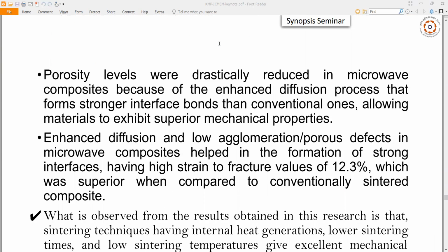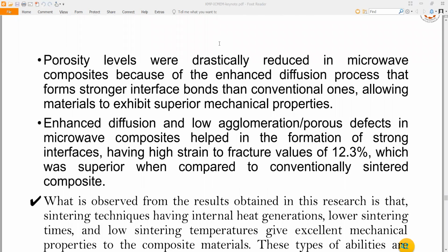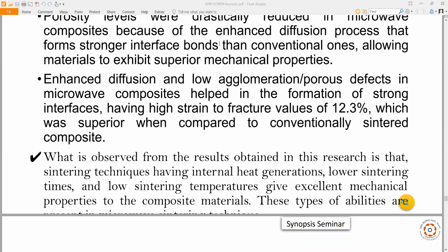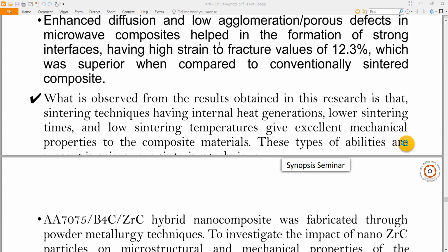Then porosity levels were drastically reduced in microwave composites because of the enhanced diffusion process that forms a stronger interface bond than conventional ones, allowing materials to exhibit superior mechanical properties. Then enhanced diffusion and low agglomeration and porous defects in microwave composites helped in the formation of strong interfaces, having high strain to fracture values of 12.3%, which was superior when compared to conventionally sintered composite. What is observed from the results obtained in this research is that sintering techniques having internal heat generation, lower sintering times, and lower sintering temperatures give excellent mechanical properties to the composite materials.